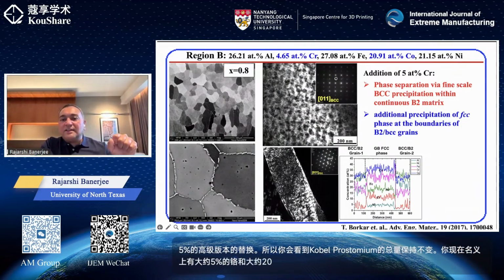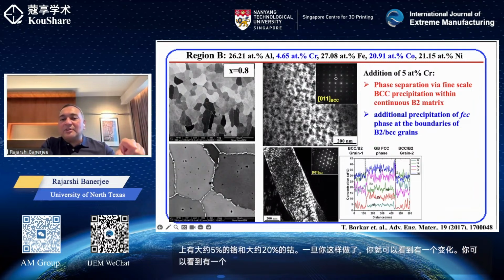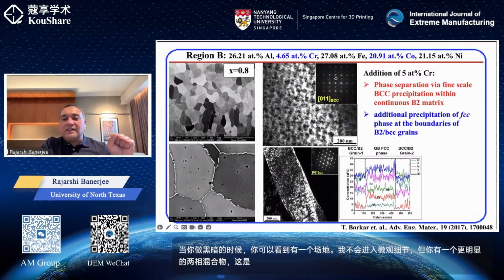When you do the dark field TEM, I'm not getting into the microscopy details, but you have a more pronounced two-phase mixture. This is a B2 plus BCC type of mixture. I'll show you that in the atom probe data also. So it's not uniform B2. And at the grain boundary, even in the SEM, you see a second phase forming, which is an FCC-like phase.